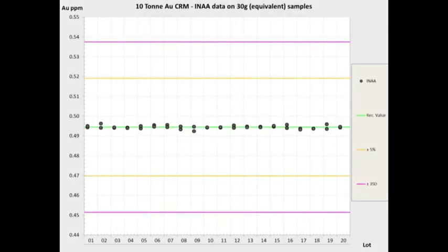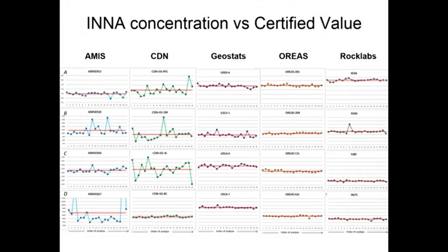There was a paper published in the Explore newsletter for geochemists by Dr. Nigel Brand, and he procured 4 reference materials at similar grades across 5 different manufacturers and submitted them for neutron activation analysis, 20 1-gram samples at Actlabs Ancaster, and here's the data. As you can see, some producers haven't gotten rid of their micro nuggets. Others have a flatter response.